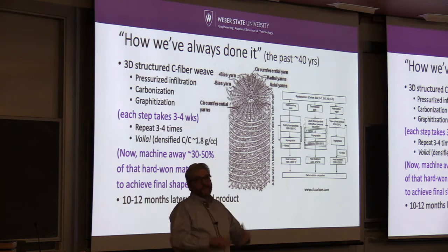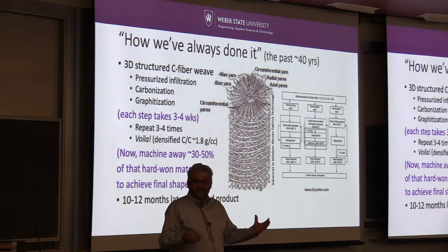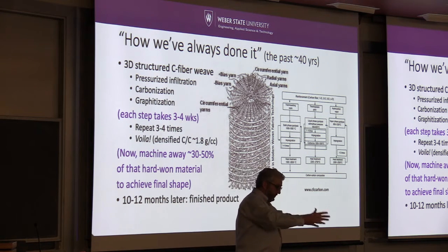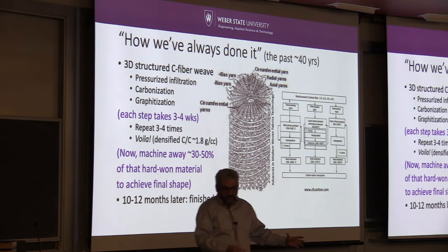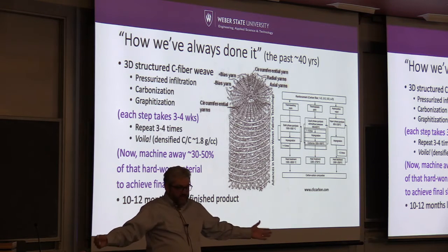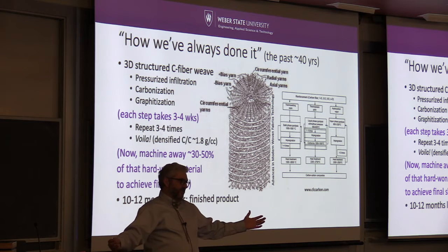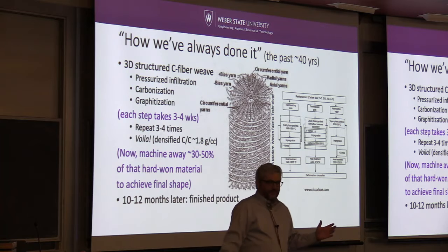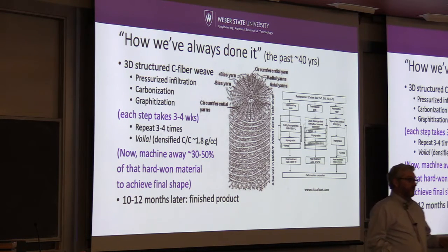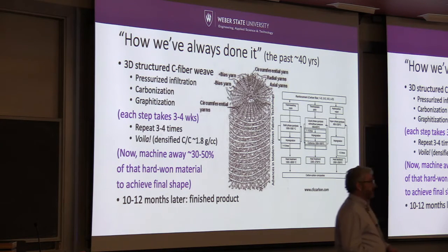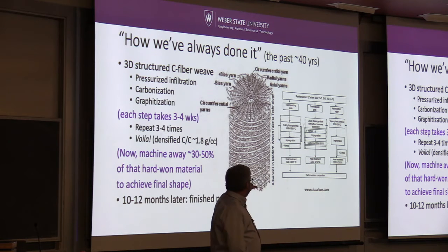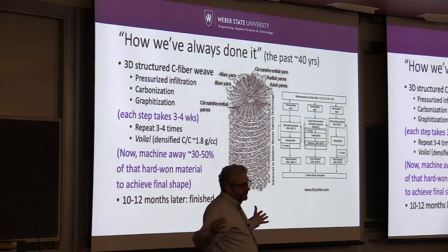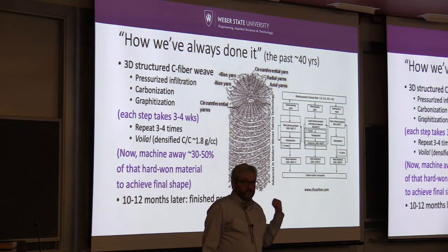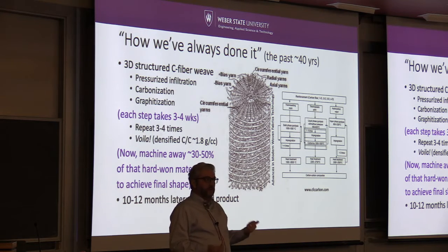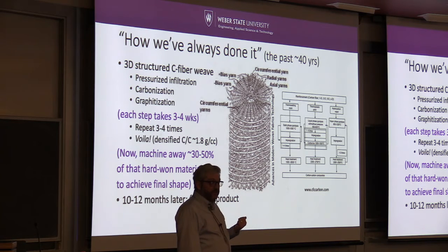Okay, well, that's carbon fiber. How do you get a dense graphitic matrix into those interstitial spaces? So here's in the factory, and you've got this billet now, and they show you how they take the billet, and you walk over into another part of this huge high bay, and there's this massive vat of stuff that looks like it came out of double toil and trouble. Fire burn and cauldron bubble. This is really some nasty looking, nasty smelling stuff, black tar pitch. And they put this billet in the pitch, close the lid, and pressurize it so it's hot under pressure, and the whole idea is to infiltrate the open spaces with pitch. Okay, this might be a thermoplastic. In this case, it was a coal pitch.